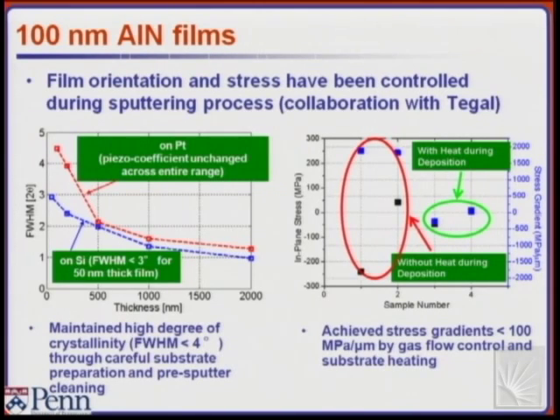The other big problem was stress. Apparently, we get huge stresses when we deposit small thin films. We can control very well the in-plane stress to plus or minus 100 megapascal, but the stress gradients are huge. These are actually probably the best results, 300 megapascal. We sometimes get 800 or 900 megapascal per micron.